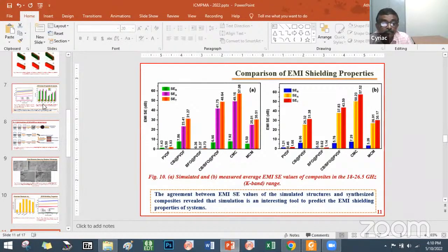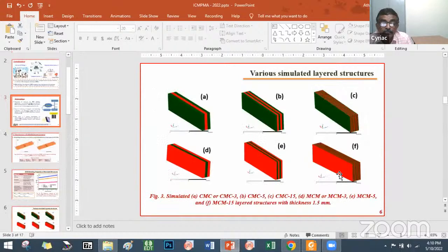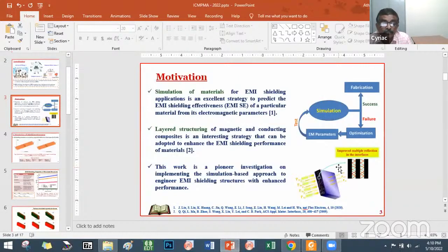What happens in layered composites is that first the electromagnetic radiation enters the material. If we provide layering, it is continuously reflected back, and further it gets absorbed by the material itself. So there will be no electromagnetic radiation coming out. It is also very important to note that we don't need primary reflections. If the electromagnetic radiation is reflected from here, it will go back to the environment only. We need a material having higher absorption potential.